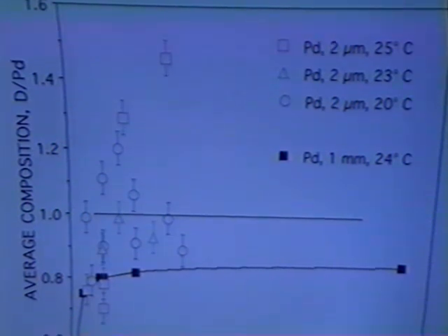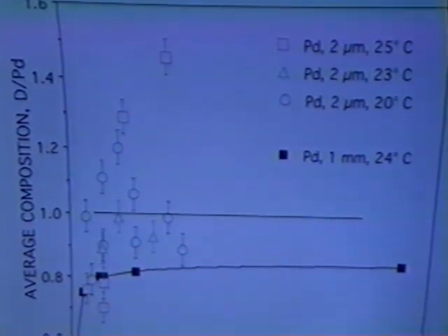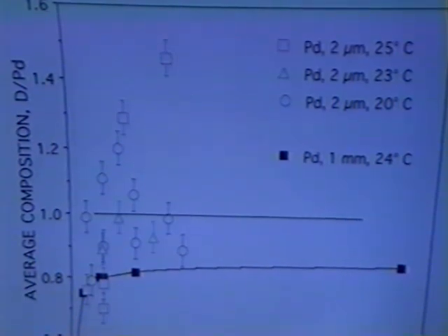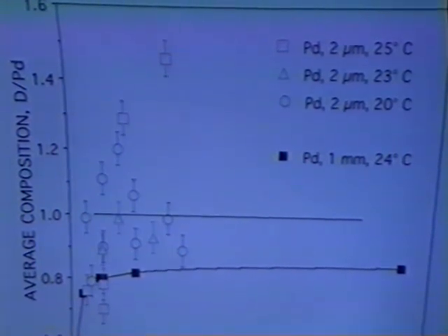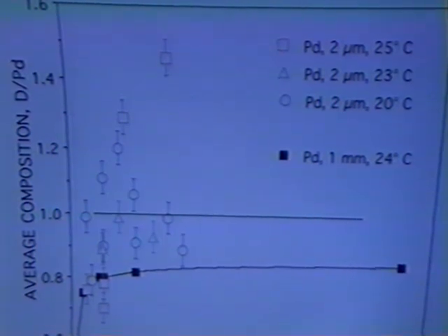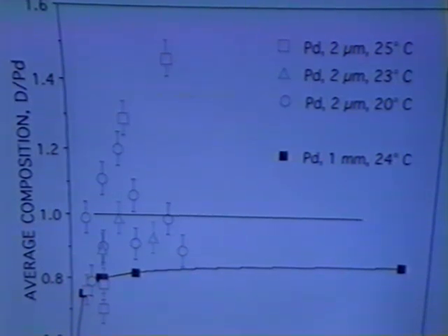At this composition, the open circuit voltage indicated that the material was not at a high enough composition to make excess energy. So the material that we're truly looking for has a composition even higher than that. Furthermore, within the 2 micron layer, this is the bulk composition, if you understand, within that layer there's also a gradient, and its surface is even at higher composition than the bulk. So I indicate that we are striving to produce a composition that's well in excess of 1.5 on the surface. And it's only when we achieve that composition that we can make excess energy.